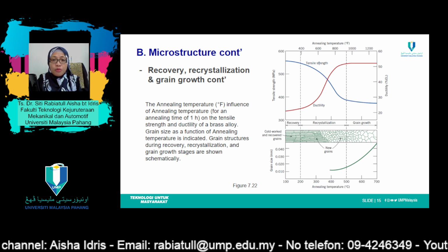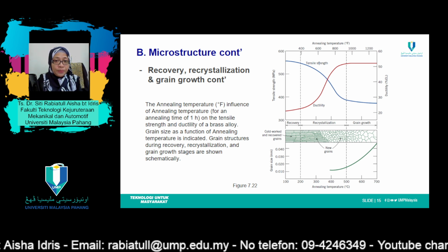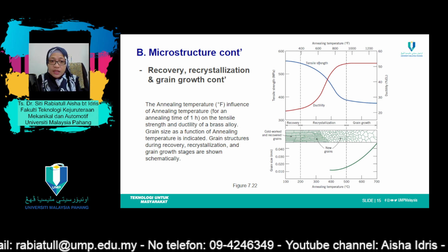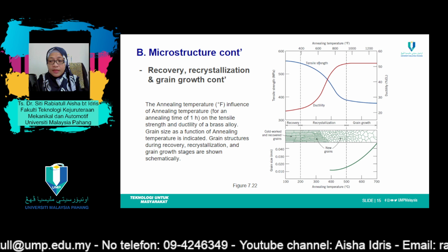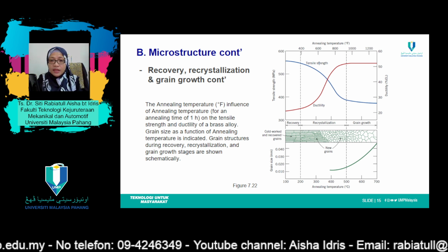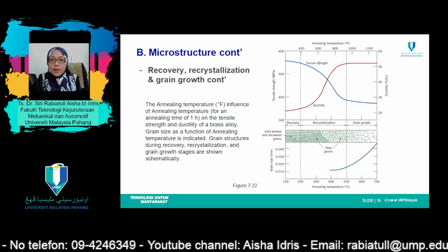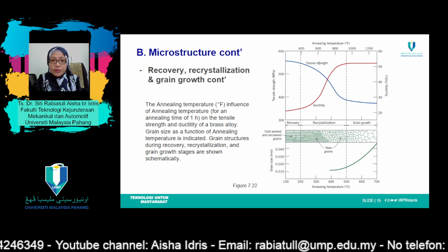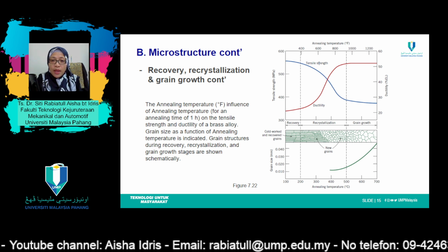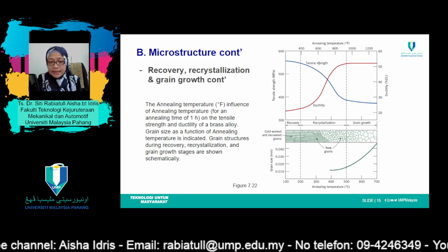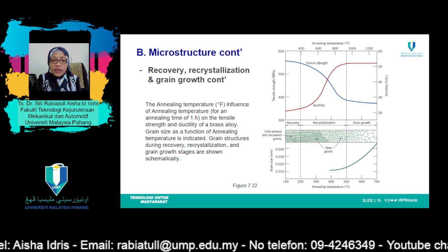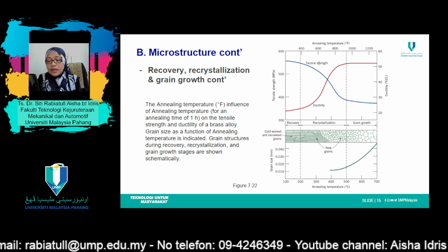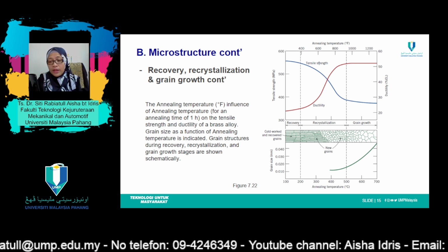Recrystallization proceeds more rapidly in a pure metal than in an alloy. During recrystallization, grain boundary motion occurs as the new grain nuclei form and then grow. It is believed that impurity atoms preferentially segregate at and interact with these recrystallized grain boundaries so as to diminish their mobilities. This results in a decrease of the recrystallization rate and raises the recrystallization temperature, sometimes quite substantially.